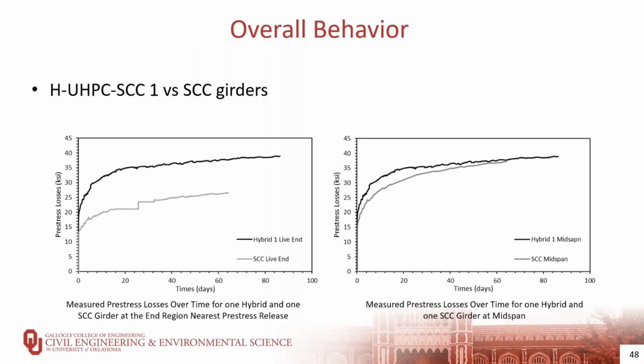So to evaluate the overall behavior of the prestress losses, we compared the overall prestress losses at the live end region and midspan between hybrid UHPC SCC1, which I'm going to refer to as hybrid 1, and the full SCC girder. Both girders were prestressed to 180 KSI, and the hybrid girder, hybrid 1, had a 5-foot reduced width UHPC section. The figure on the left here shows the measured prestress losses over time for hybrid 1, or the UHPC SCC1, and SCC girders at the UHPC end region.